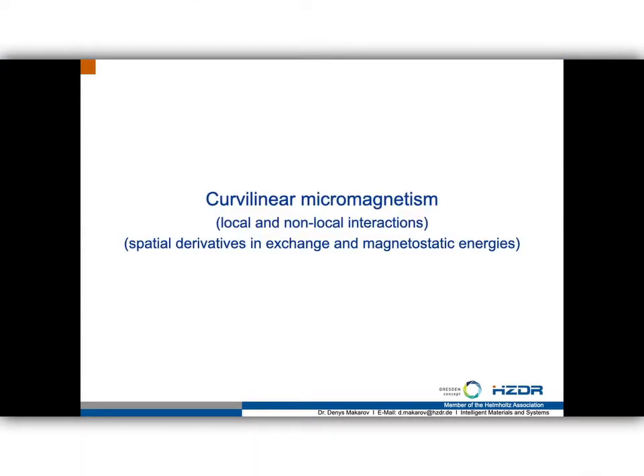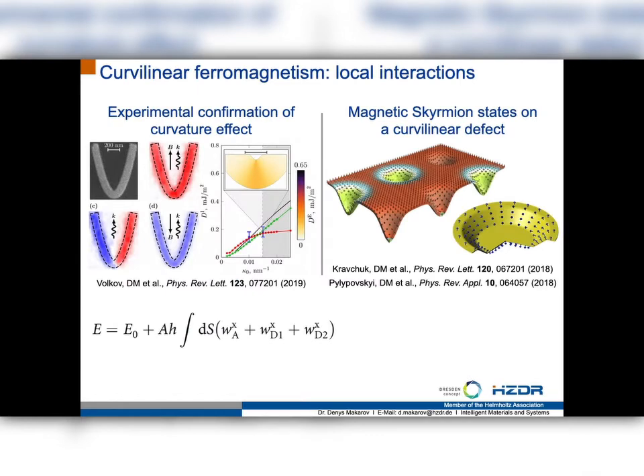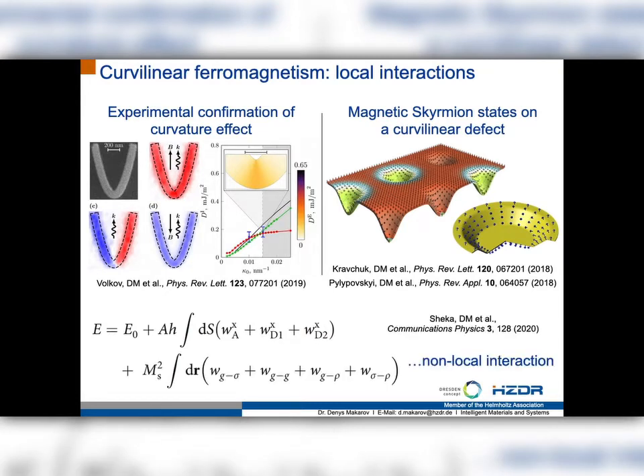Everything we discussed before was about local interactions. So everything induced by geometry was effects which came from the spatial derivative of the exchange interaction. Of course, what makes magnetism very exciting, where you have domain walls, for example, domains in your system, is micromagnetism, where you also consider magnetostatic interaction, where non-local effects come into play. So everything we discussed before, like this parabola, pinning of domain walls at the parabola, Skyrmions and Skyrmionium states, for this you need only the approximation where energy terms only up to the first linear term in thickness are considered. As soon as you make the next step, which was done recently by Denis Sheka, you will necessarily get non-local interactions in the system, and those interactions are, of course, very complex to analyze, but they bring very interesting physics into your system.